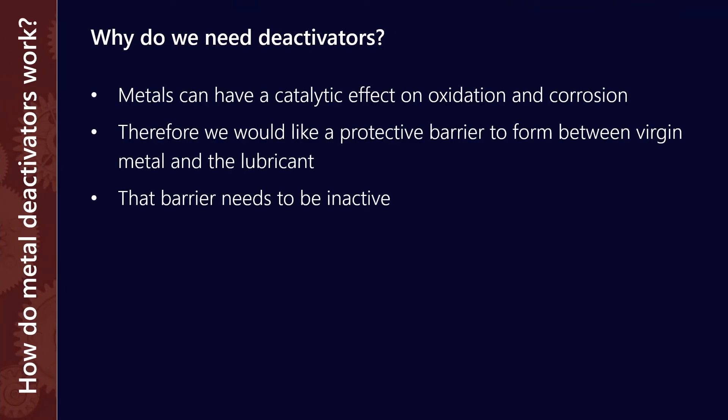The first question is why do we need metal deactivators? The problem with metals is that they can have a catalytic effect on both oxidation and corrosion. If you had, for example, a new copper cooler in an engine and you get some copper migrating into the lubricant, probably in ionic form, each of those ions can act as a site that promotes further oxidation and therefore the aging process of the oil. So it can accelerate the breakdown of the base oil.